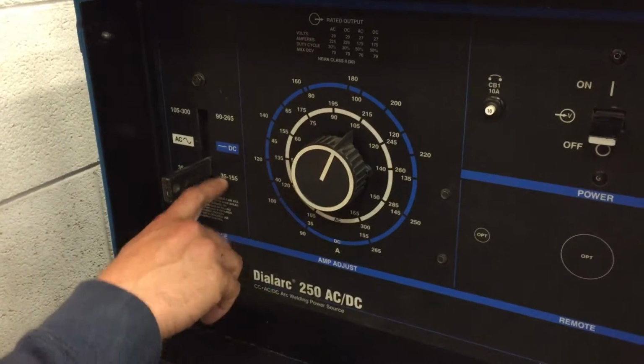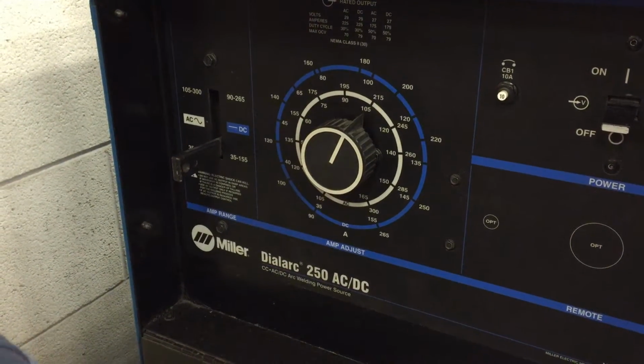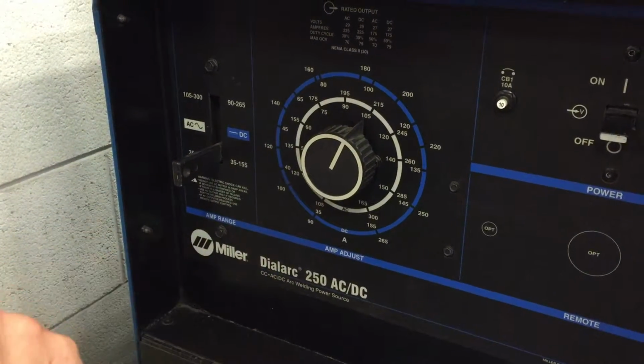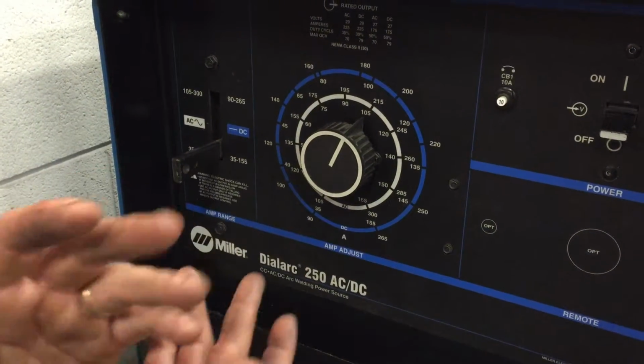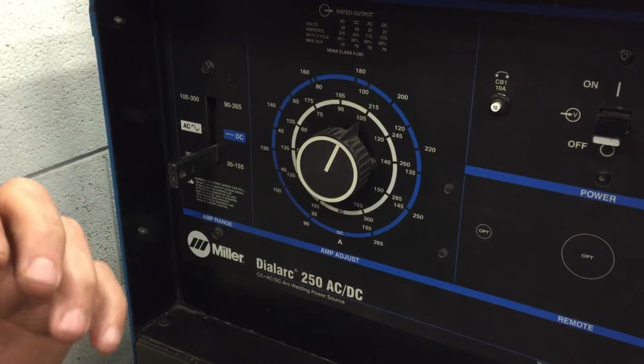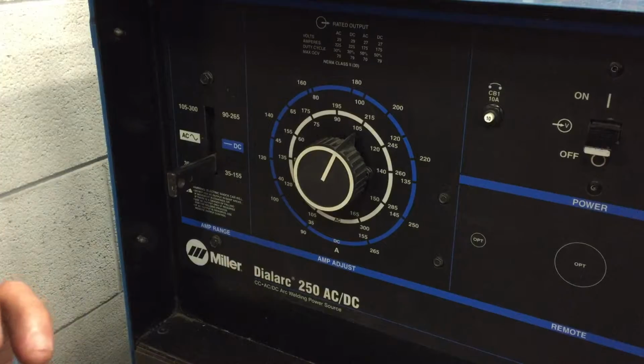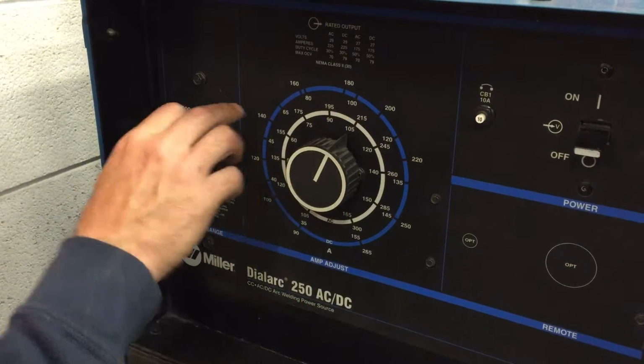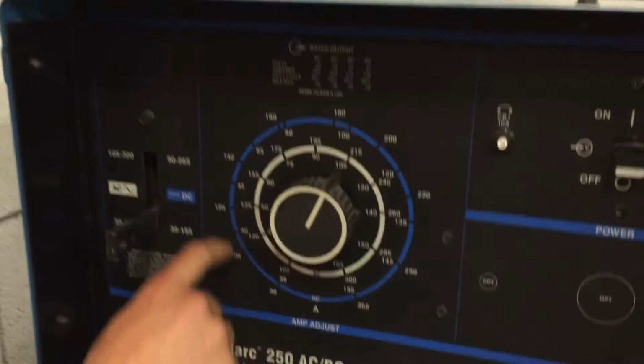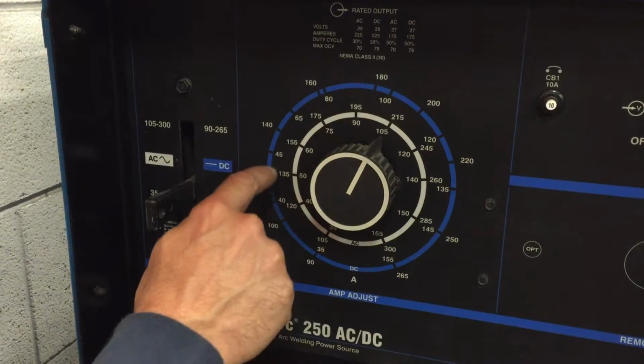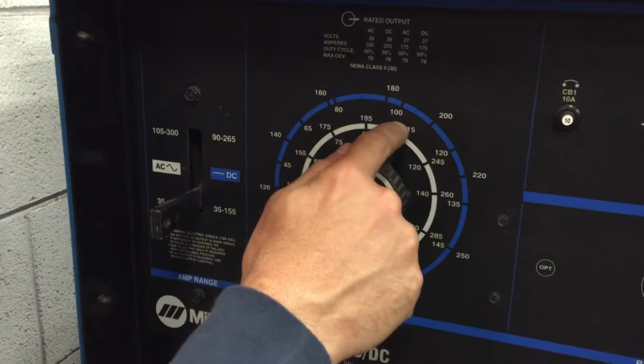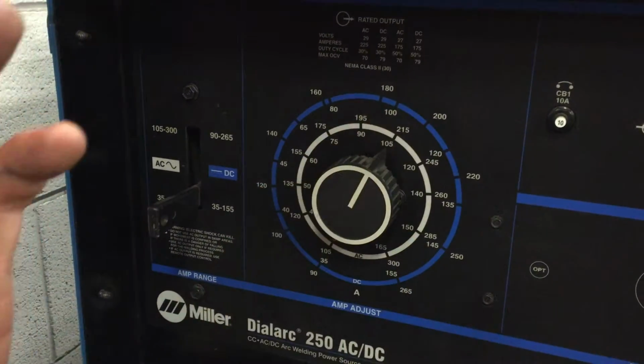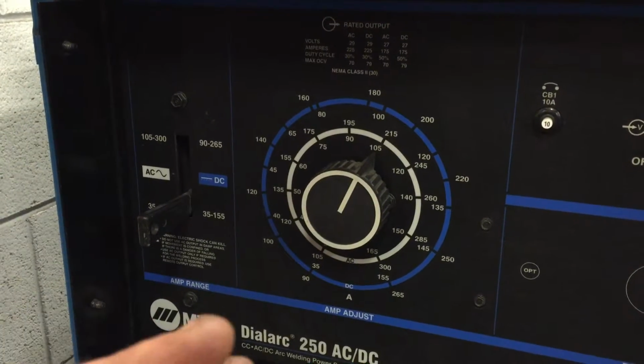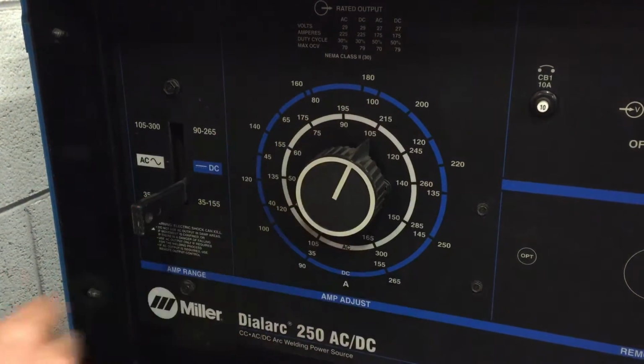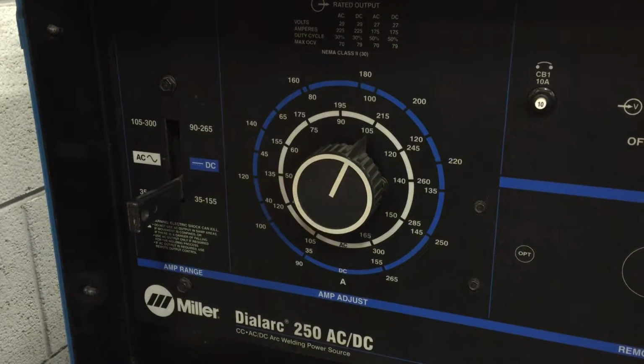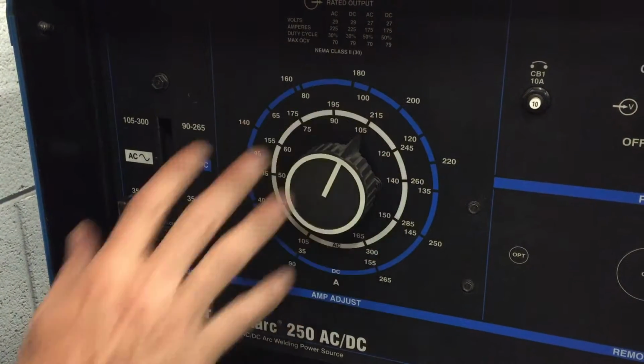So now this welder has a high side and a low side. The differences are subtle between the two. I like the low side for flat welding. I like the high side for vertical welding. Vertical, I seem to have a little better arc stability on the high side. But since we're on the low side, we're going to be on the blue line. The inside numbers associated with that blue line, we're going to weld somewhere between 100 and 120 amps. That's my recommendation. Other people weld a little different. My recommendation for flat welding though is 100 to 120 amps.